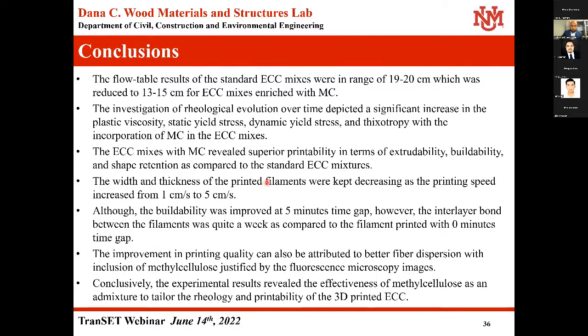Regarding the effect of printing speed, we observed that with increasing speed from 1 centimeter per second to 5 centimeter per second, the printing dimensions such as width and thickness kept decreasing. So this shows that we have to adopt an optimized printing speed for our mix to get better results in terms of printing quality.